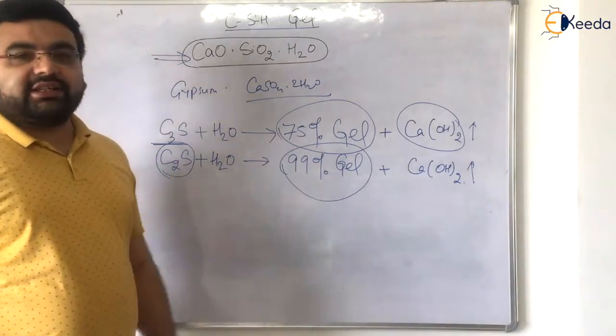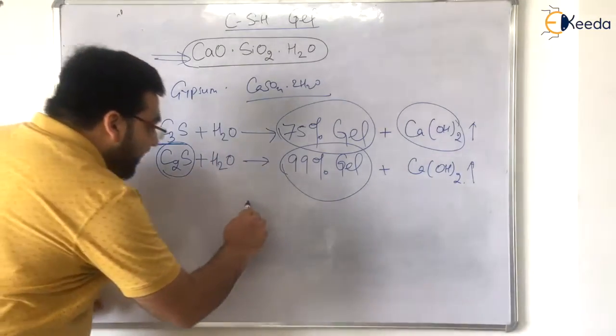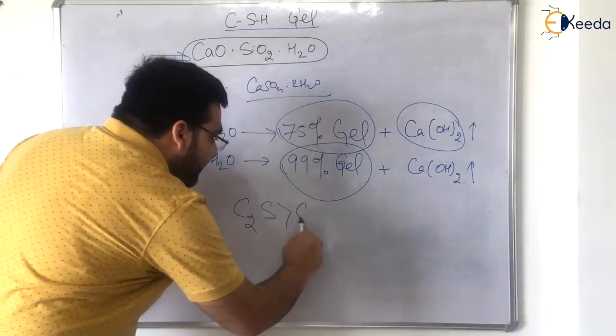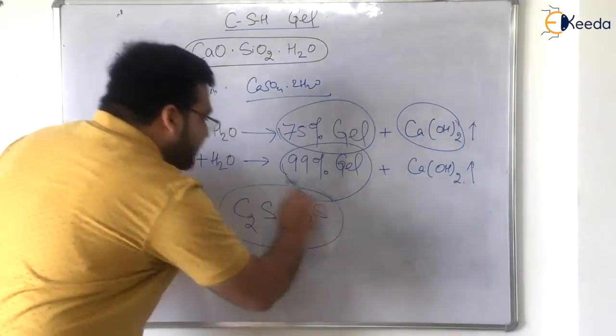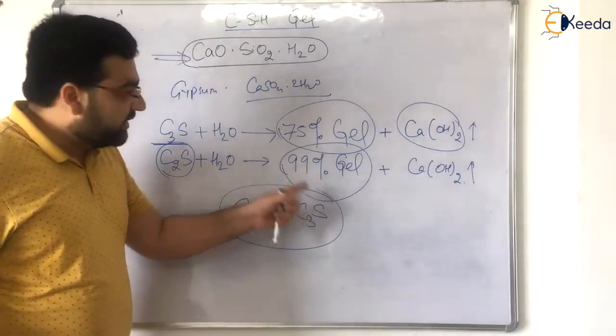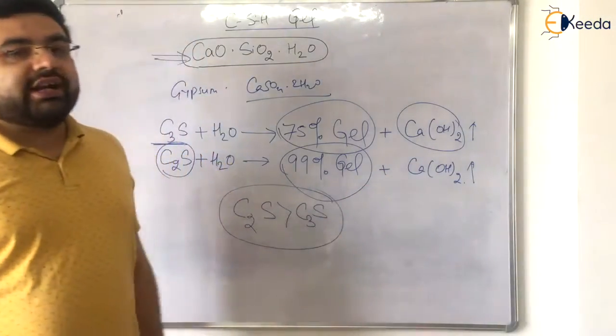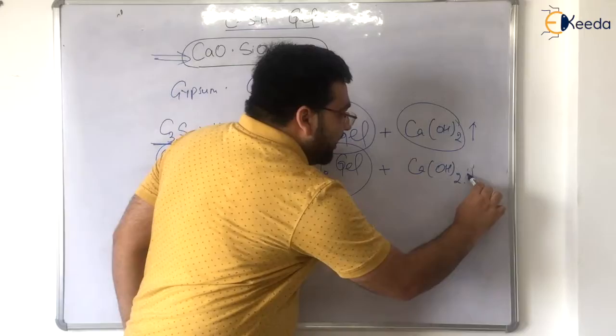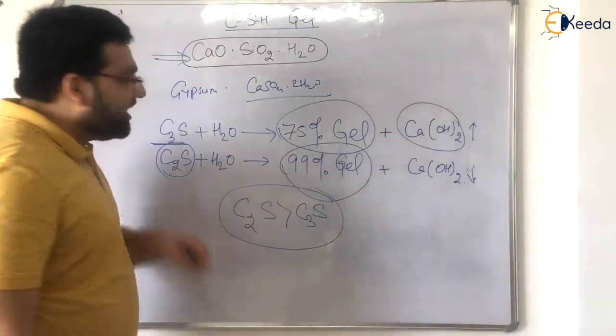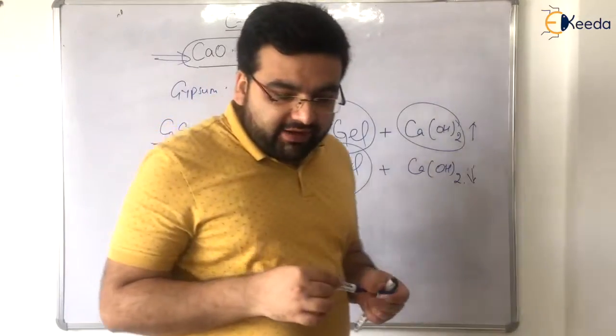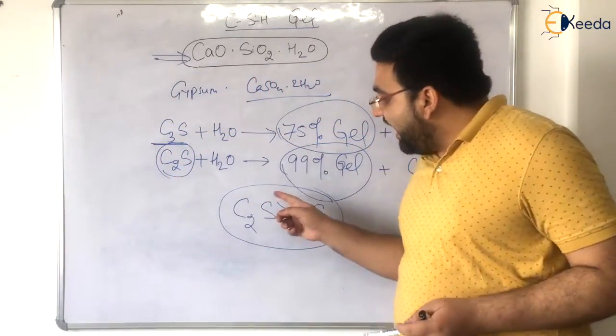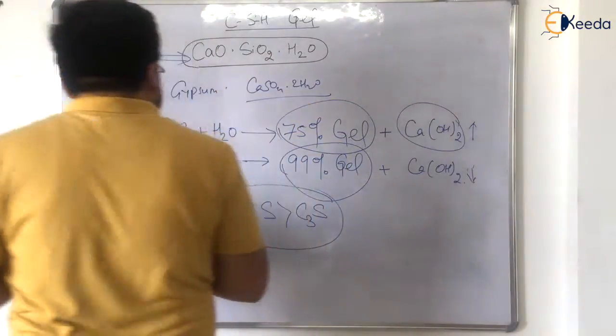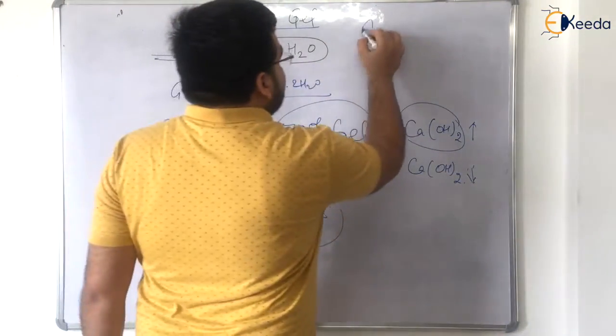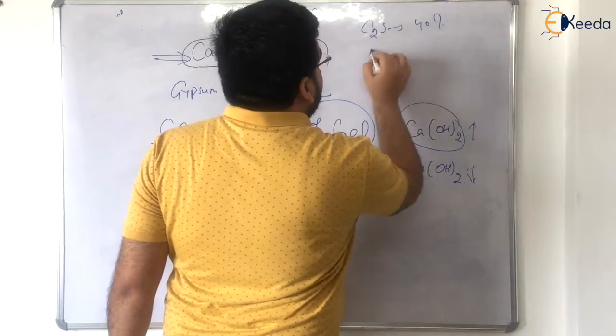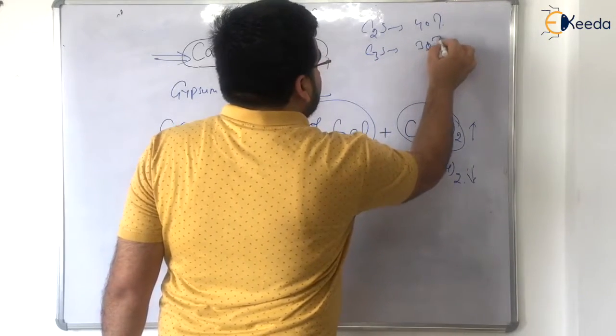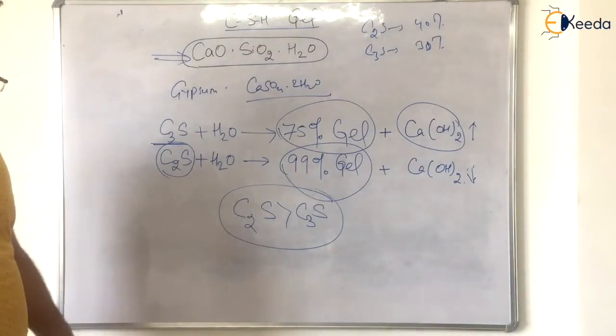This is the only reason, I am again repeating, why C2S gives greater later strength than C3S. The first reason is 99% gel. The second reason is that calcium hydroxide is formed in a smaller amount as compared to C3S. Because in the table I told you that C2S is about 40% and C3S is about 30%. I told you 32%, right? That is the only reason.